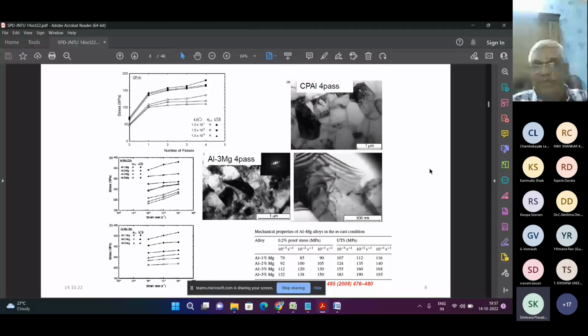So we have taken aluminum 3 magnesium, which exhibits superior properties when you consider the ductility and the strength. So this material we have taken. Why? Because what we wanted to do is not only aluminum magnesium alloy, we have added some scandium, a rare earth element, to this one, and tried to see how improvement can take place. And we have taken the pure aluminum magnesium alloy, and we have passed one pass, two pass, three pass, four pass. And you can see in the middle one how the mechanical properties are increasing, YS, that is yield strength, and UTS. Both the things we have evaluated.